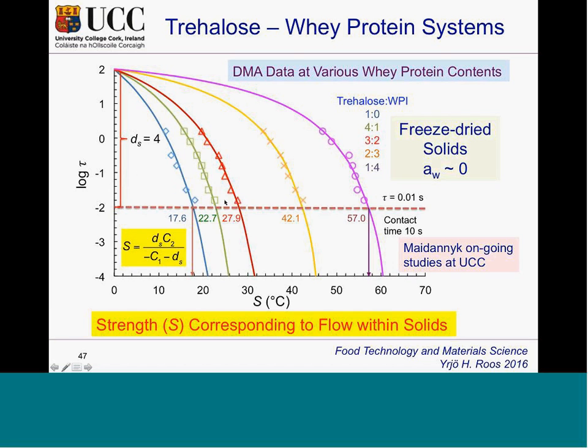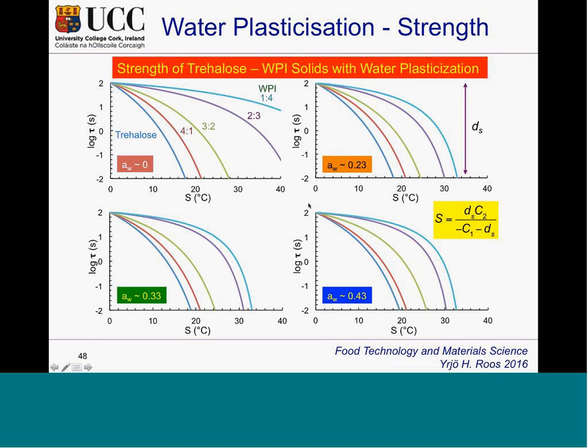I can apply that with materials that we know and use it when we want to determine this in spray drying or freeze drying, collapse, and so on. So we know how much we can exceed the glass transition. If we add water to the material, we would see that there are also changes in these parameters, and the more water we have above a critical value, we get very rapid changes. The food composites.